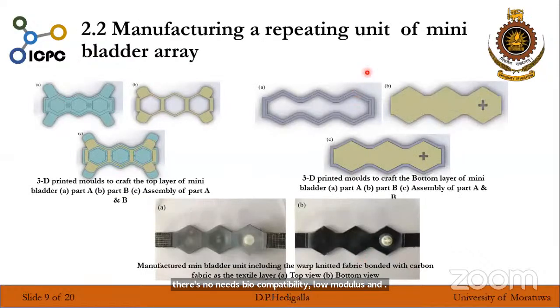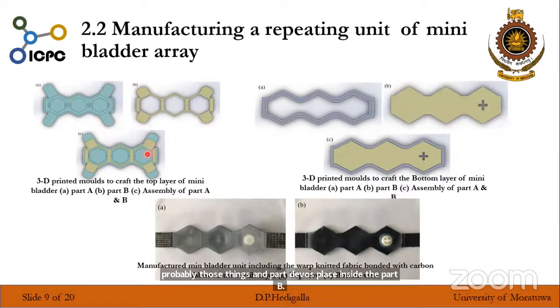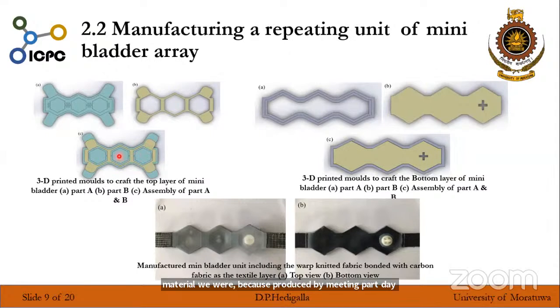So here is the mold that we have used to manufacture the mini bladder unit, and here are mold 1, part A and part B. Part B was placed inside part A, and then the silicone material, which was produced by mixing part A and part B in a 1:1 ratio, was poured into this and kept for curing. And once it's cured, the top layer was peeled off.